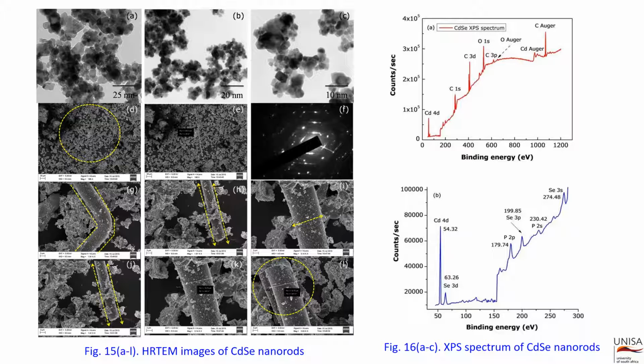The formation of individual nanorods of cadmium selenide with a narrow size distribution is evident from the HRTEM images. Figure 15E shows the lattice fringes of a single nanorod, and the clearly visible lattice planes endorse the formation of a well crystallized single crystal cadmium selenide nanorod.